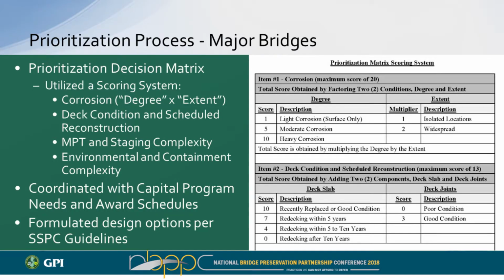We used the VIS standards to identify our amount of corrosion that Mark and Aaron were talking about earlier. For corrosion, for example, we took the degree times the extent. So how much? Was it light? Was it moderate? Was it severe? And then was it localized or was it widespread? We assigned points to all these and came up with an actual solid single number at the end, which would give us an idea of, okay, this is the worst case scenario, and it sort of gets better as you go down the list.